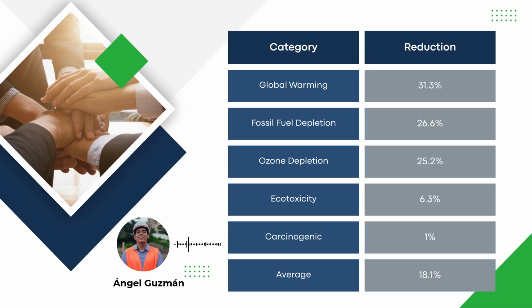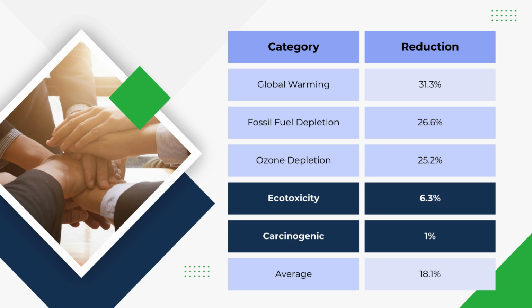An 18.1% environmental impact reduction was achieved based on 5 key categories. The most significant improvements were global warming, 31.3%, fossil fuel depletion, 26.6%, and ozone depletion, 25.2%. However, toxicity and carcinogenicity showed minimal reductions, 6.3% and 1% respectively. These low scores are mainly due to the continued use of Portland cement, which is highly polluting and difficult to replace. GGBS was avoided due to its low impact and silica fume due to the cancer risk, but silica remains present in cement-based materials.